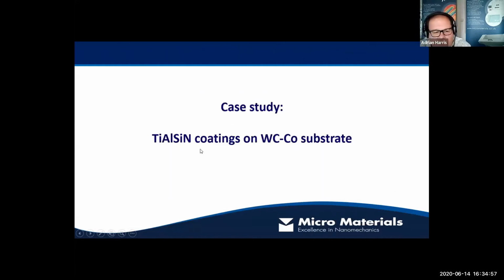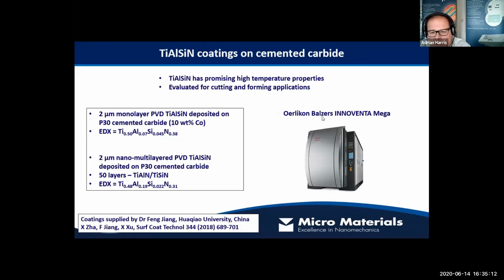So let's actually use it now for something. So this is a case study. It's two titanium aluminium silicon nitride coatings on a cobalt bonded tungsten carbide substrate. So both the coatings are on exactly the same substrate material. The coatings are supplied by Huaqiao University in China. They're both 2 microns thick. So we have an analysis from EDX of the composition of the coatings. So they're kind of similar.